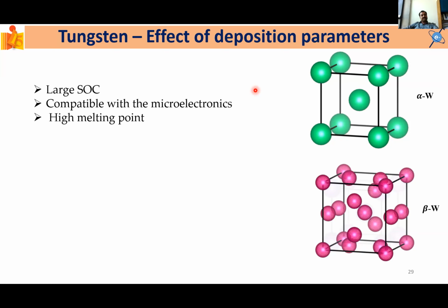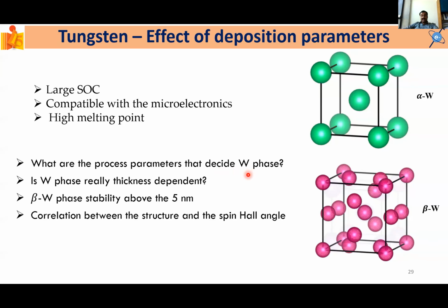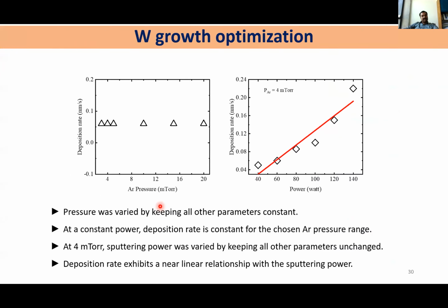So we have tantalum, tungsten, and platinum. The largest spin orbit coupling can be found in tungsten, and it is also compatible with microelectronics, and it has a very high melting point. Our interest is to find out what process parameters can affect the tungsten phase, and is it really thickness dependent? There are some reports that say beta tungsten cannot be stabilized above 5 nanometer. We wanted to see whether we can do it and finally find a structure and spin Hall angle correlation.